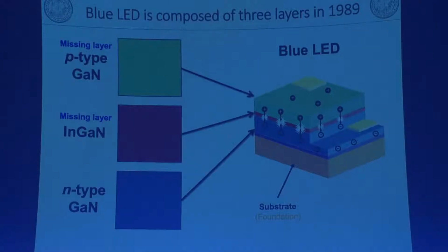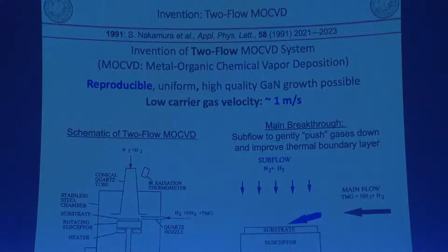So basically, we need 2 layers. I told you, indium gallium nitride and p-type gallium nitride. So I had to develop these 2 layers. Initially, I purchased an MOCVD, a reactor to grow gallium nitride, because the founder gave me $5 million. I purchased a $2 million MOCVD, and I tried to grow gallium nitride for a couple of months, but no crystal growth, 0. Even the growth was a black color of gallium nitride.